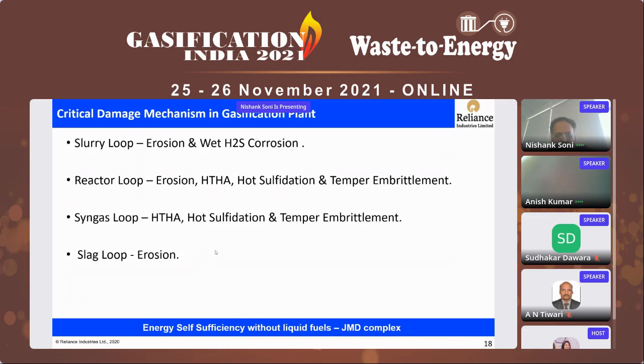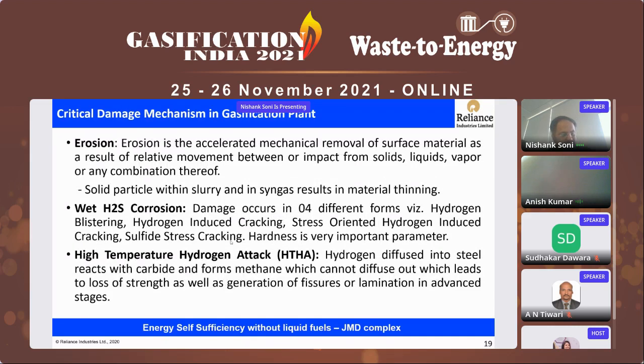Since this syngas is cooled significantly and solid particles are sieved away, except for erosion, all the other remaining damage mechanisms will be the same as the reactor loop, and they will also remain active in the piping and equipment of this particular loop. For the slag loop, since it contains water with solid slag particles, erosion will be the only active damage mechanism.